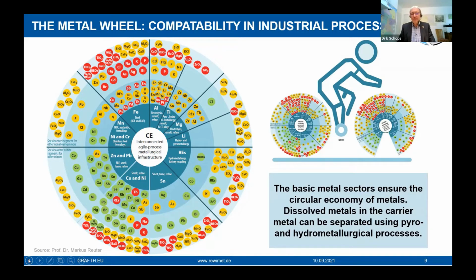Of course, it's no problem when you have an alloy which is just used for the same purpose again. Then it's no problem to have a ferrous alloy, iron-based, for instance, with chromium and nickel and so on. Then it's no problem, of course, to melt it and use it as an alloy again. But it's hard to separate the metals if you would like to do this. It's rather hard. And I guess in that case, it's only dependent on the kind of melting temperature of the metal itself.